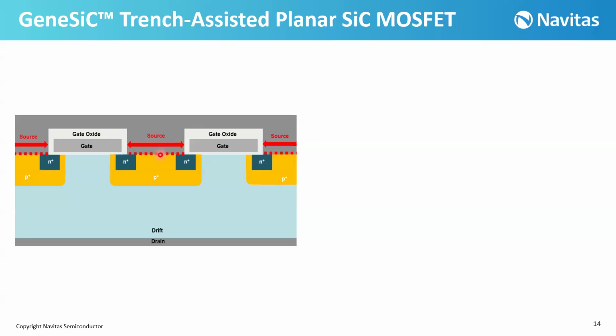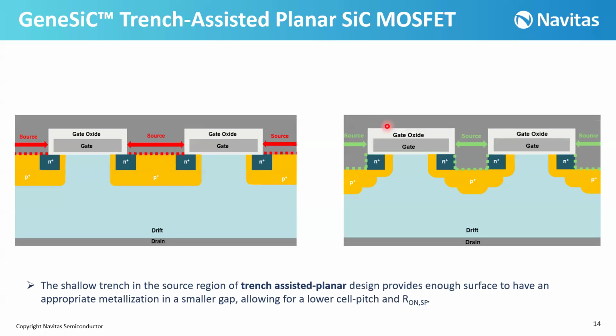Actually, we need a good metallization here for the source contact. And for having a suitable metallization, we need enough surface in order to make this metallization. And it makes a limitation for shrinking or reducing this source pad area, the source area gap. But by our technology, with having this shallow trench, we are making enough surface in order to have a good metallization. And by this, we can reduce the source gap and reduce the cell pitch. And this is another reason that we can reduce the RON,SP.